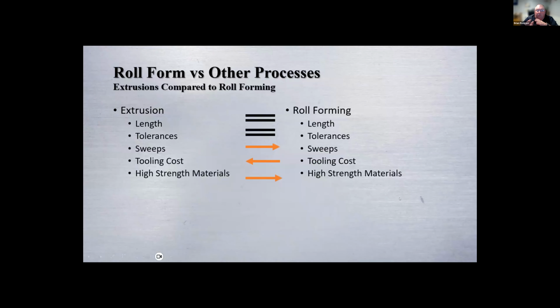It's just the product. So when we compare them, length, yes, an aluminum extrusion can make very long parts or very short parts. Tolerancing on the profile, aluminum extrusions hold very tight tolerances on the profile. But when it comes to putting a contour in the part or a sweep, you have to go to another operation to do it, where we can do it in line on a roll former.